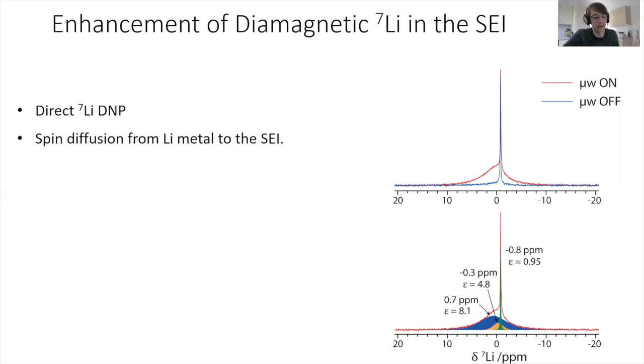The lithium fluoride is sort of the easiest to distinguish because it's the only thing we should see in the lithium to fluorine CP. The other species overlap a lot, and so we do have a more detailed discussion in the paper about what exactly we can potentially assign shifts to. It was only really the lithium fluoride that was very definitively much higher enhancement than other species, and therefore was definitely at the surface. Everything else was a little bit less clear-cut.